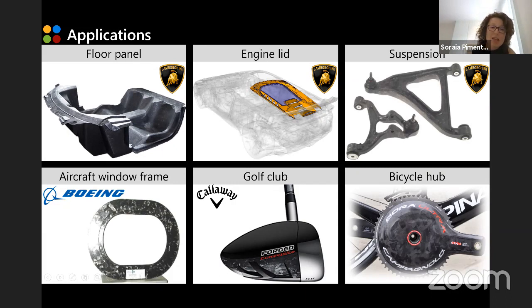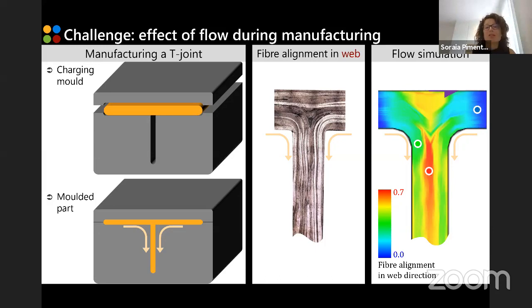But we still have some challenges, and one of the challenges comes directly from the advantages in terms of manufacturability. So if you think about what happens when you manufacture a T-joint, as I showed in the previous slides. So we have a charge, and the beauty of these materials is that they can be processed by compression molding. So you can just apply heat and pressure, and the material will flow and fill whatever mold cavity you have. Now, what this means is that the fibers will align themselves in the direction of the flow. And this means that we are going to have properties that are going to be different from one point to another. So here on the right-hand side, you can see that we can predict this effect of orientation of the fibers in the direction of the flow by simulating the manufacturing process itself.